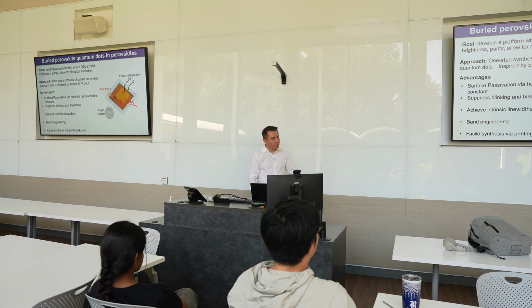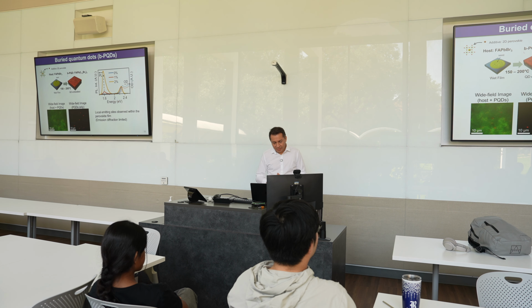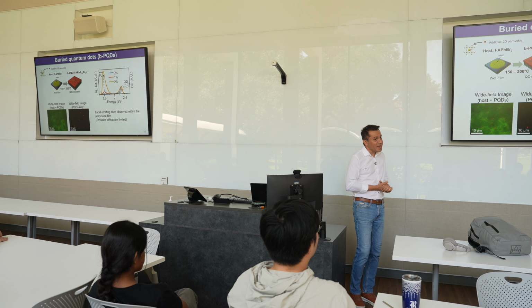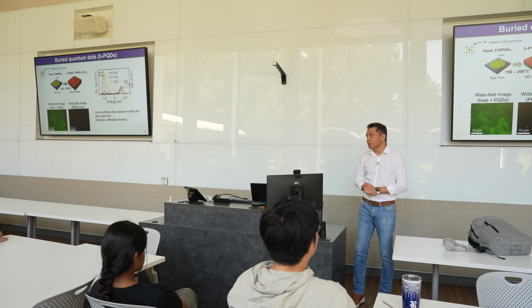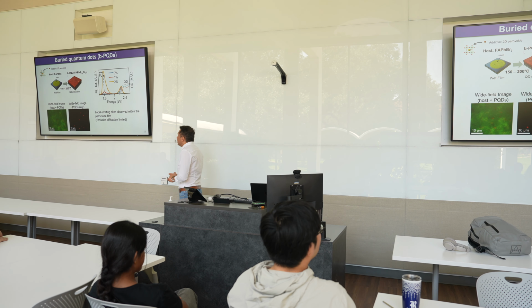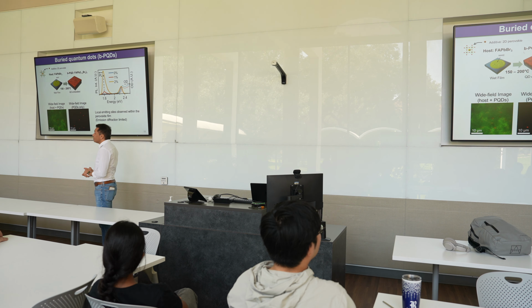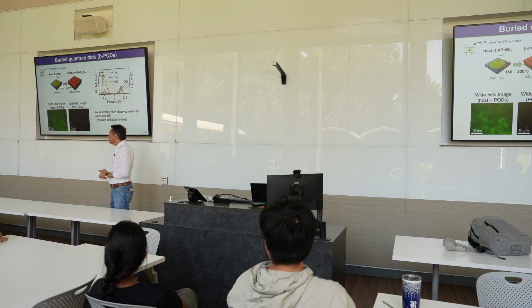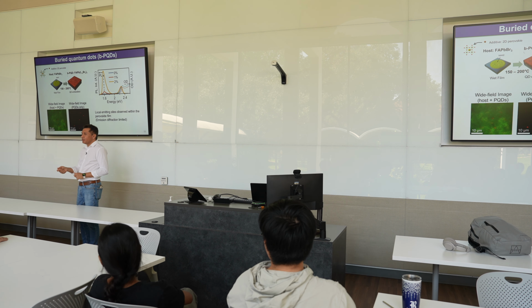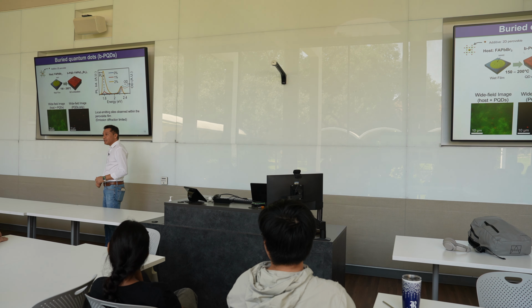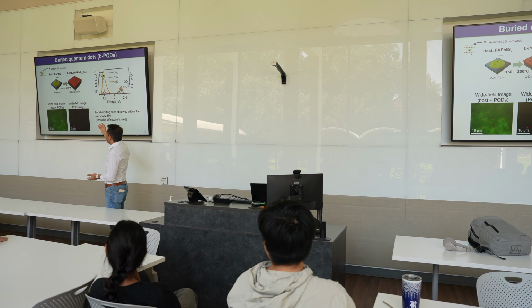And I want to be able to print this. If I can print these materials in a facile way, I want all of these things. That's asking a lot for a material system to do. So we've developed this process where we can make these embedded quantum dots inside a host of a 3D perovskite. It's really simple. We take one of these halide perovskites, formamidinium lead bromide, and we add a type of additive, which is an iodine source. For example, we'll add a 2D perovskite which has iodide in it, and then we do a certain annealing step. What we end up getting is we grow quantum dots, but now they are embedded inside this 3D matrix. That's what that cartoon looks like.